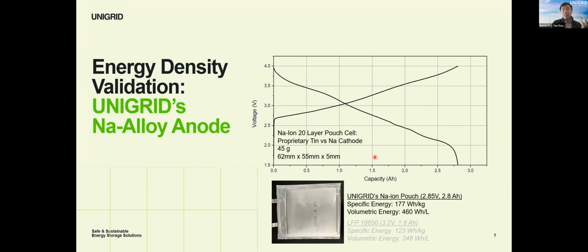To validate some of these energy density claims, one of our early works, when we just came out, was to validate this in a pouch cell. So this is one of the very first pouch cells we made. This is a 20-layer cell. It uses our proprietary tin anode versus a commercial sodium cathode that we buy off the shelf. And it's 45 grams in weight, pretty standard dimensions.